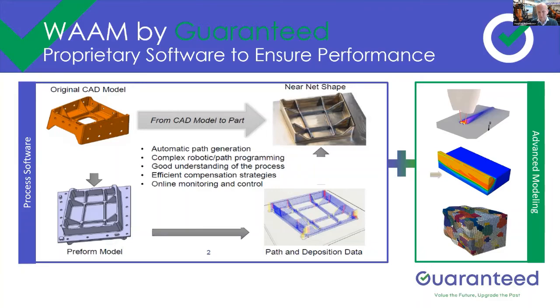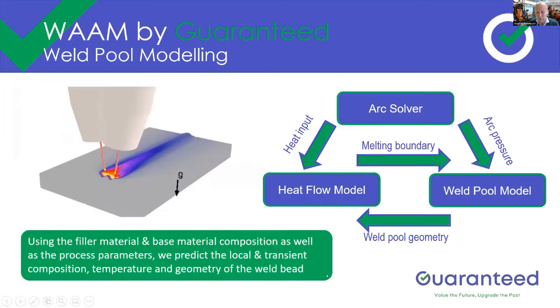And I'll explain in the next couple of slides a bit more in detail what exactly we're doing in that respect. So of course, the first step is to understand, if we're running our process, what is the heat which we're putting into the material. For that, we developed a full weld pool modeling software solution, which you see here on the slide, where we're using the composition of the filler material and the base material, as well as the process conditions, in order to predict the local and transient composition, temperature, and geometry of the weld bead. This way we get a full picture, on the one hand of the geometry of the bead, but also of its composition, as well as the transient heat behavior of the component.